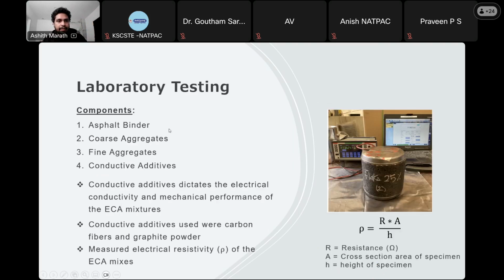So with that, for the laboratory phase of the study, I just included a single slide. It is basically to develop the ECA mixture, the electrically conductive mixture. The components of the mixture are the typical components such as asphalt binder, coarse aggregate, fine aggregates, and conductive additives. Conductive additives give the property of electrical conductivity to the materials. In my study, I used graphite and carbon fibers as the conductive additives.